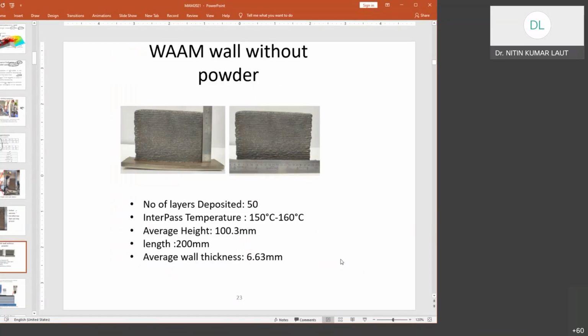Okay. So there is a comparison where we have used wire with powder and without powder, so that we have a better understanding of the role of the nano powders we are using to generate the layers. These are some of the parameters: 50 layers are being deposited, and you see another important thing, where these researchers have tried to ensure the interpass temperature between two layers. So this is one layer and this is the other layer, and the temperature in between these two layers is called the interpass temperature. They have an infrared temperature measuring device, and they have ensured that it drops to around 150 degrees centigrade, plus or minus. And after that, they deposit the second layer.